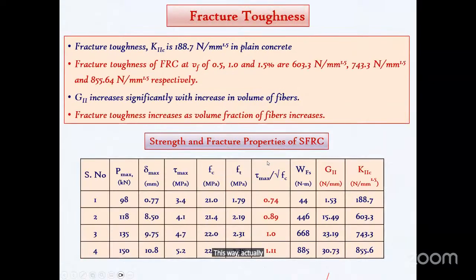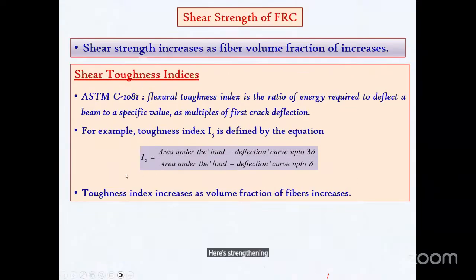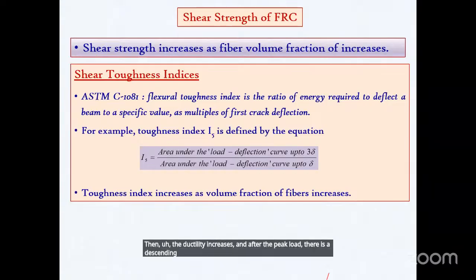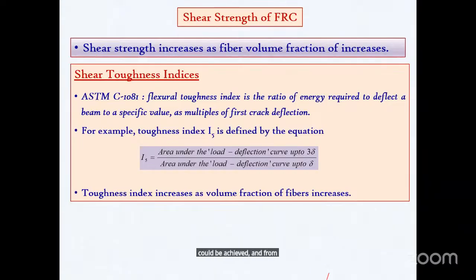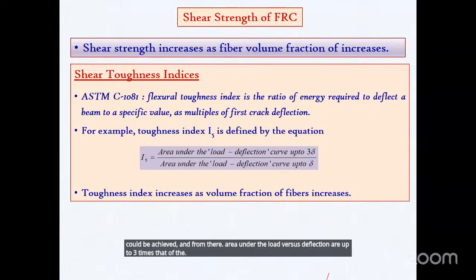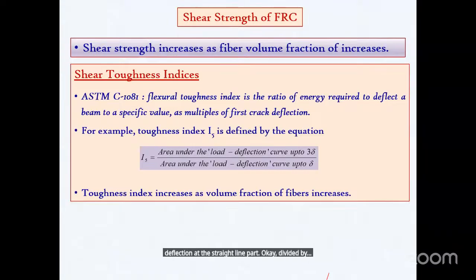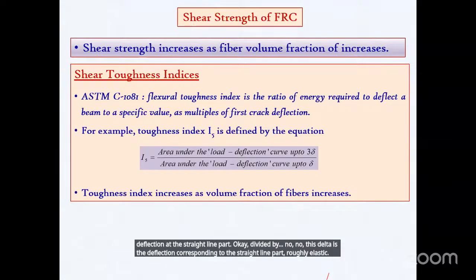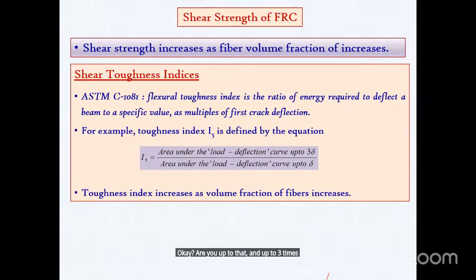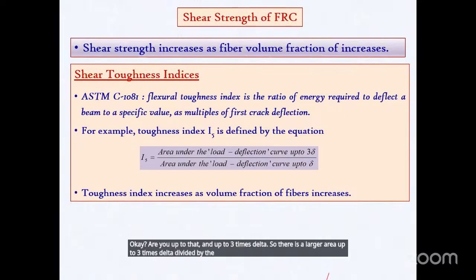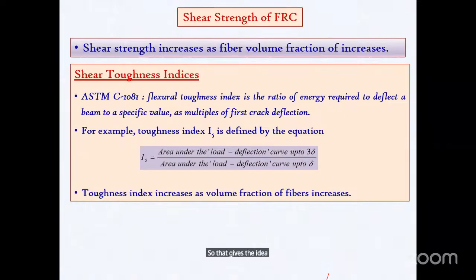This way, the toughness of the concrete was investigated, and we found that as fibers are added to the concrete, they influence the failure mechanism and also the shear strength. Shear strength increases, and there is one index. The index is calculated as the area under the load. So as the number of fibers added in concrete increases, the ductility increases, and after the peak load, a long descending curve could be achieved. From there, the area under the load versus deflection curve up to 3 times delta, where delta is the deflection corresponding to the straight line part, roughly elastic, is divided by the area up to only delta. So that gives the idea how ductile the material is.